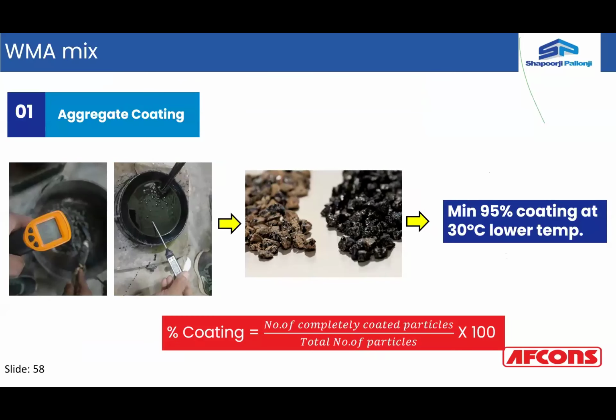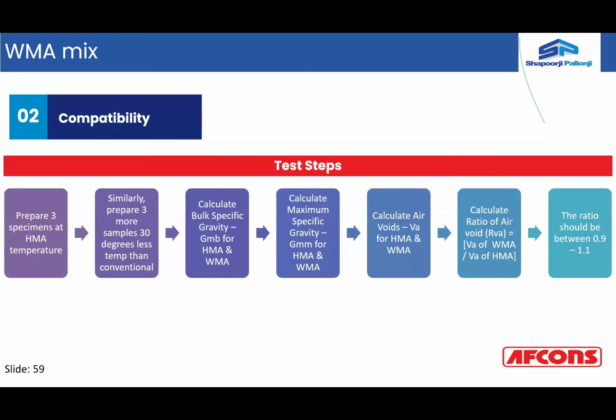Yeah, when the same mix was introduced to the heated aggregate, see, the coating should not be less than 95% at a lower mixing temperature of 30 degrees less. So if you want to calculate the percentage coating, the number of completely coated particles divided by the total number of particles taken for testing, multiplied by 100, will give you the percentage of coating, and that percentage should not be less than 95%.